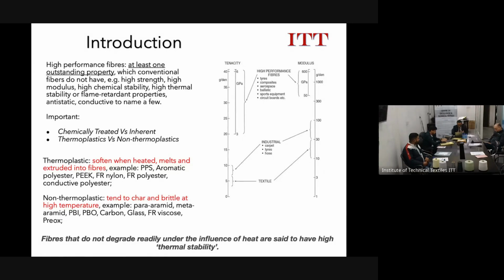So for protective textiles, which is our area, strength is one requirement. Sometimes we need strength, but most of the time we are looking for thermal stability. We want our materials, our yarns, to be thermally stable. That means they should not degrade under the influence of heat. Say we are keeping a glove at 180 degrees centigrade or 200 degrees centigrade for 50 hours or 100 hours. It should not lose its cut performance or heat performance. So for us, thermal stability is very important, I would say on top of strength.